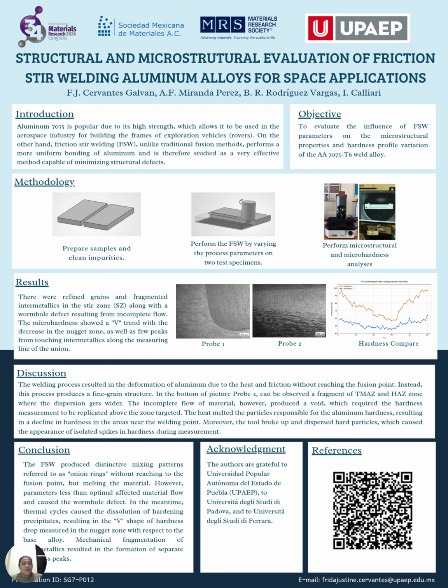For the results, we have that there were refined grains and fragmented intermetallics in the stir zone, along with a wormhole defect resulting from incomplete flow. The microhardness showed a V trend with the decrease in the nugget zone, as well as a few peaks from touching intermetallics along the measuring line of the union.